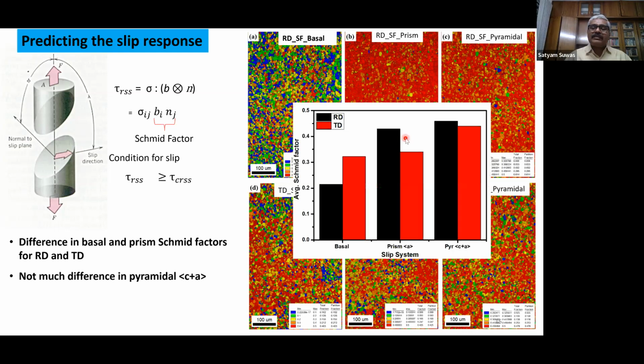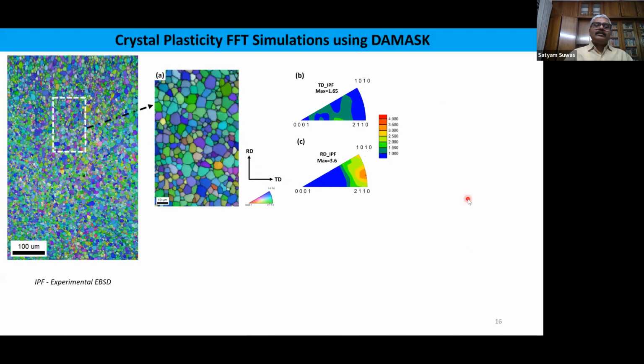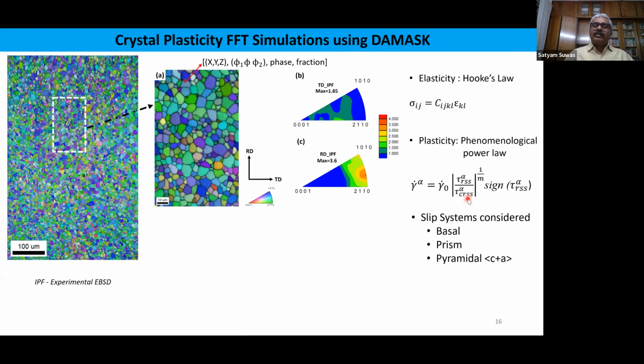Here it's more clear, extracted from the same data, where we could see that the average Schmid factor for basal slip was lower for a rolling direction sample and higher for a transverse direction sample. And similarly for prismatic slip, the order was reversed. And for pyramidal slip, it was almost similar with a little bit of difference, right? This was also subjected to investigation.